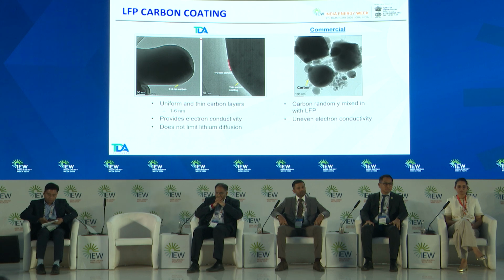One other advantage we have with our process is the fact that we make the LFP and the LMFP material and coat them with carbon in a single step. In the commercial process, you end up making the LFP, LMFP, and then add carbon to it. As you can see in the pictures, these are TEM, or very high resolution microscopy images.